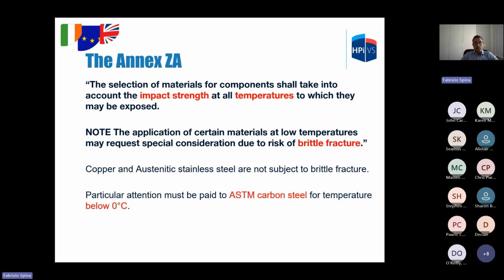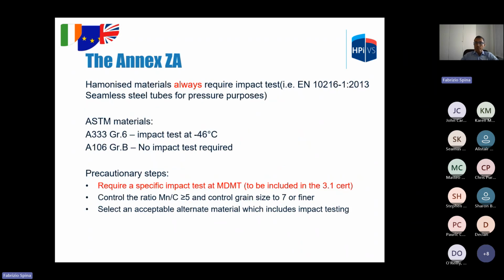Copper and austenitic stainless steel are not subject to brittle fracture. So when you use copper or austenitic stainless steel, you can ignore the impact strength and brittle fracture, but particular attention must be paid when using ASTM carbon steel for temperatures below 0. Harmonized material, for example EN 10216, always requires impact testing. So when you are buying material according to a harmonized standard for a carbon steel, it will always be provided with an impact test.